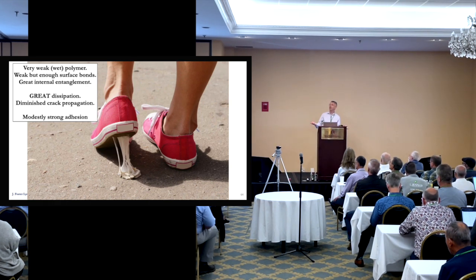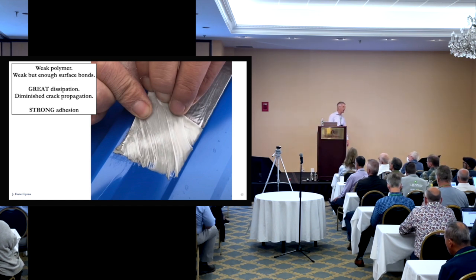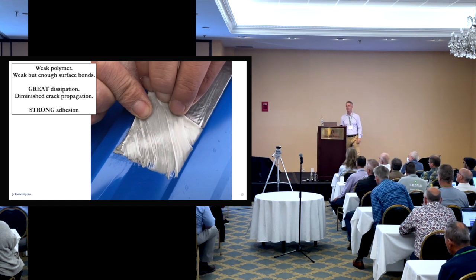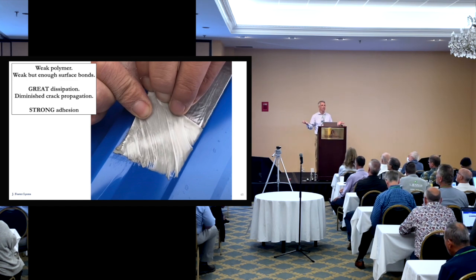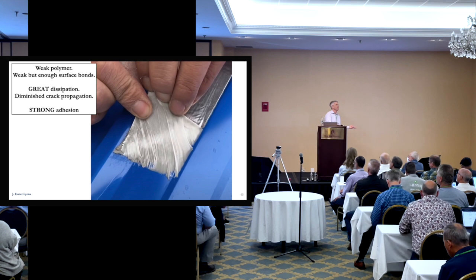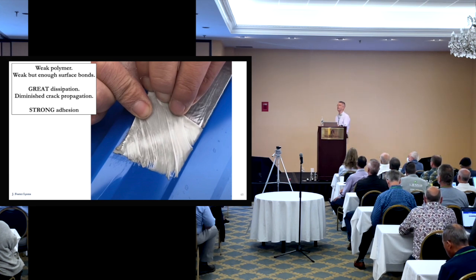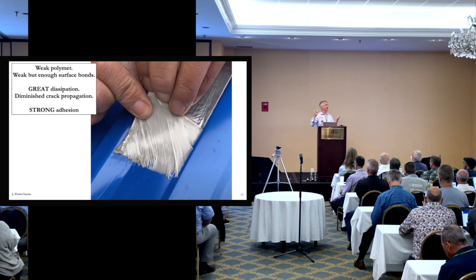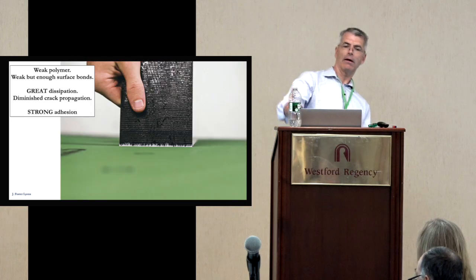This is modestly strong adhesion, and that is the way our practical adhesives work in our industry, all right? And this is just another picture, same thing. It's a weak polymer. You can tell it's weak because when you pull it and it really stretches like that, that's an indication. But there's enough of these very weak surface bonds. There's not some crazy chemical bond between the polymer and this painted metal. It's not like some fancy chemist came in and made some super strong bond. No, it's a crappy, weak bond between the polymer and the paint. The forces applied by this person trying to pull the tape off are dissipated in the material, and that's what gives it the strength, okay? Great dissipation, strong adhesion.